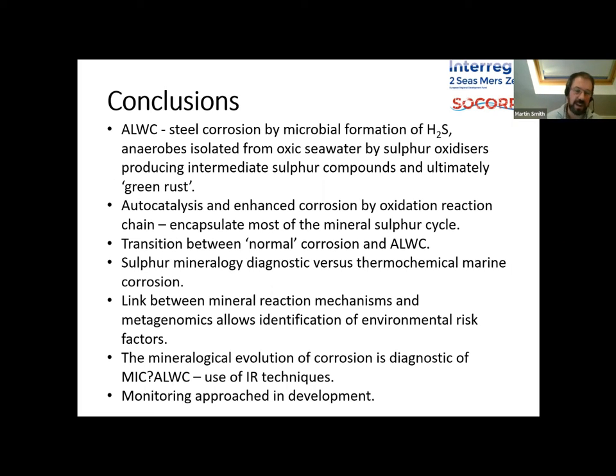We're increasing pH, we're producing microenvironments within corrosion that encourage further development of sulfate reducing bacterial colonies. And it encapsulates most of the mineral sulfur cycle. And that transitions between normal corrosion and these microbially influenced forms.